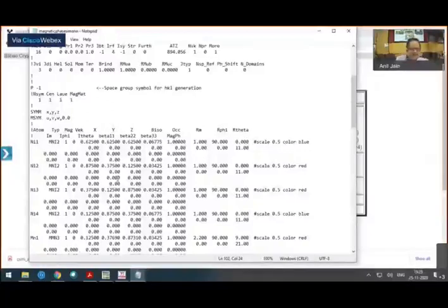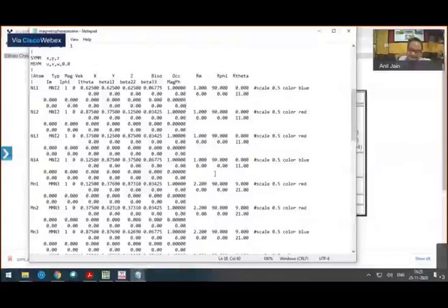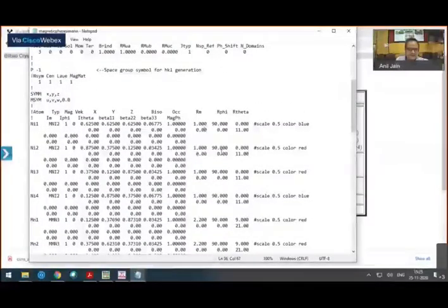Then, what is the idea? Now you are writing the moment of each individual atom. But this is a very tedious exercise in this case, until you have some idea from some experiment or from some literature that the moment has some direction. So here what I have done is I have written this moment in terms of spherical coordinates, meaning r, phi and theta.